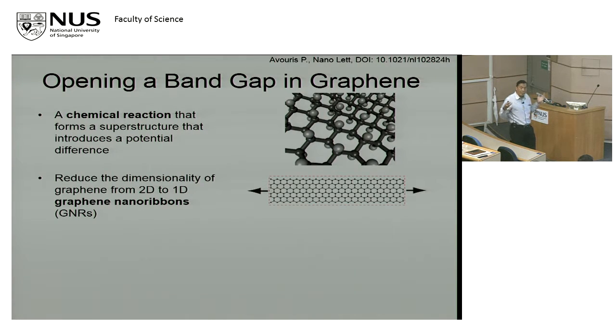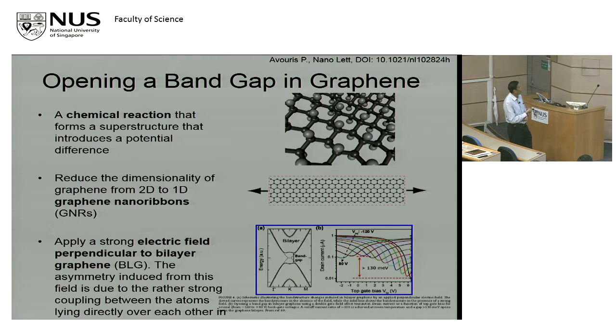Another way is you reduce the dimensionality, because physicists will tell you that if you reduce the dimensionality of things to a small length scale, then you get quantization of energy effects. So you make a 2D sheet into 1D nanoribbons, you can open a band gap. And another way is to use bilayer graphene, apply a perpendicular electric field, create asymmetry between the two layers, and you open a band gap. I'll just say we did explore these two things, okay?